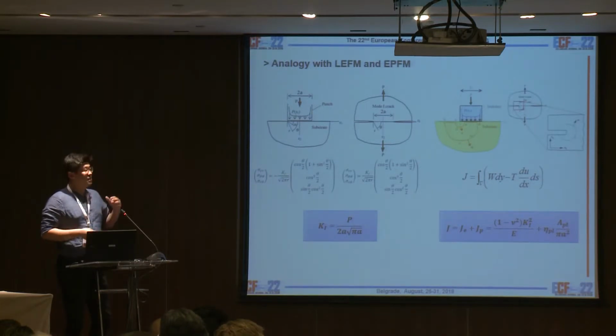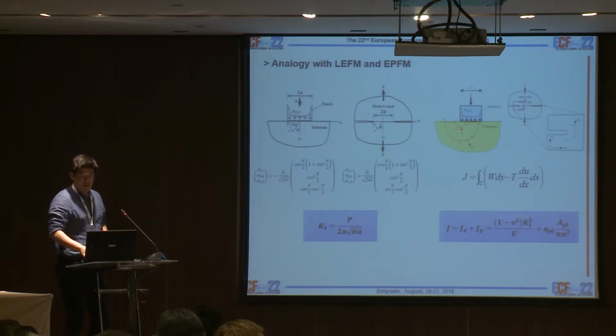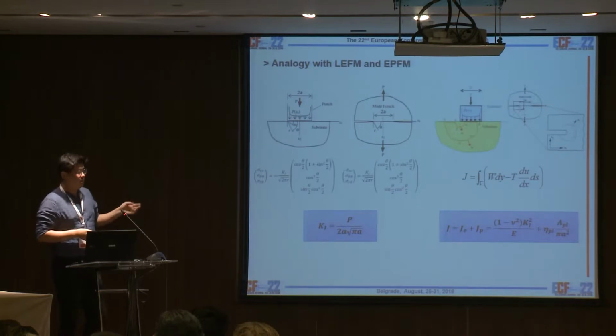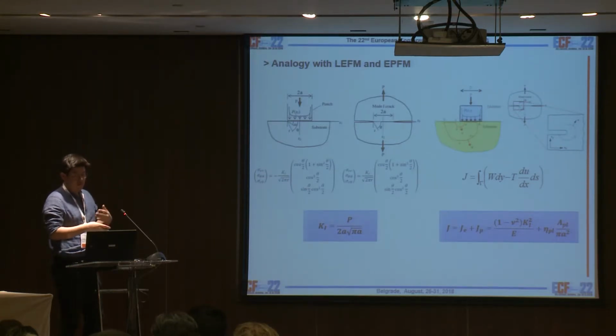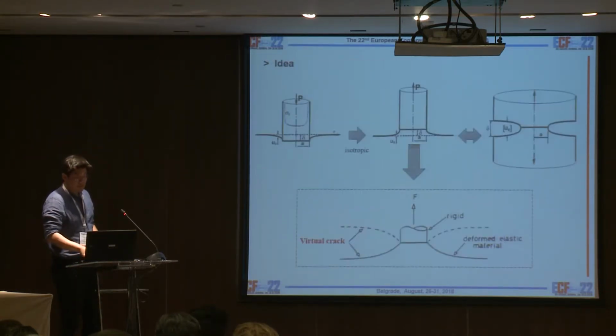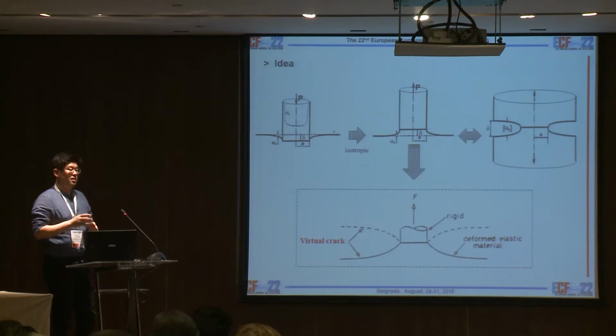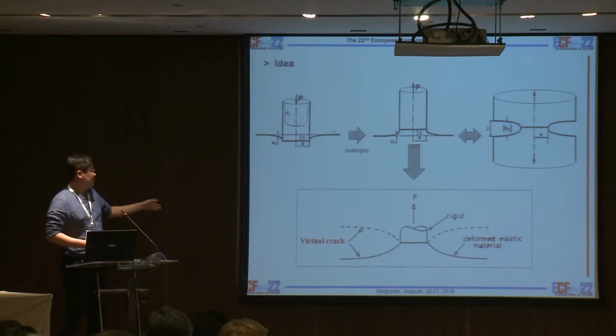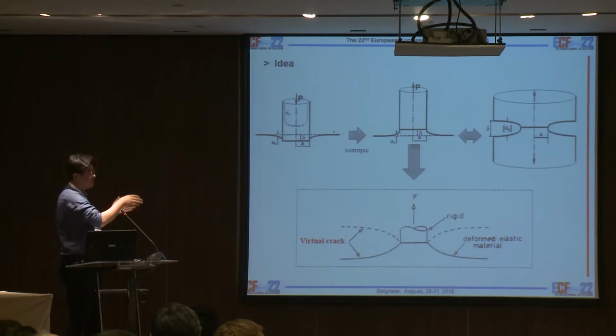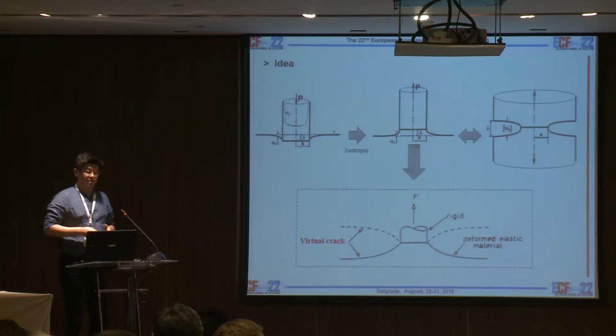Moreover, researchers analyzed the stress field beneath the indenter in terms of fracture mechanics, and they reported that the two analogies are not perfectly the same, but somehow a similar state will occur during the indentation. So here is our idea. We did the flat punch indenter test and assumed the material is isotropic, so the compression state is the same as the tension state. Then we can imagine a virtual crack line here, and then we can say the state is similar to the cracked round bar fracture toughness specimen.